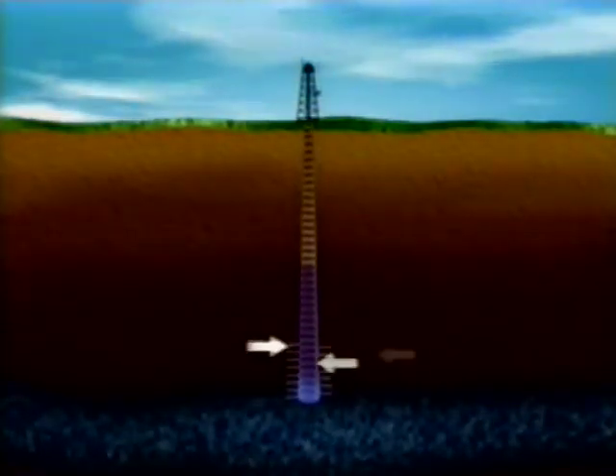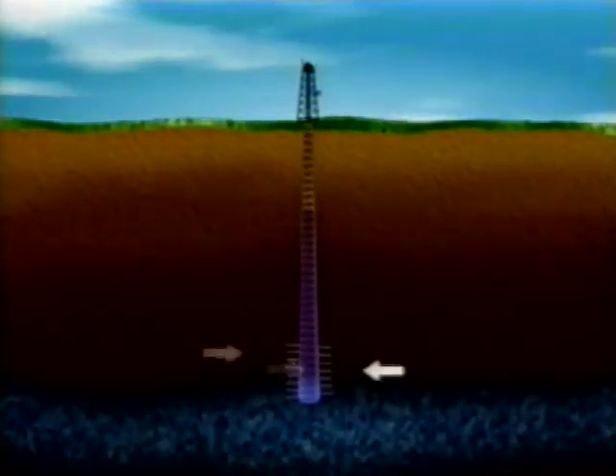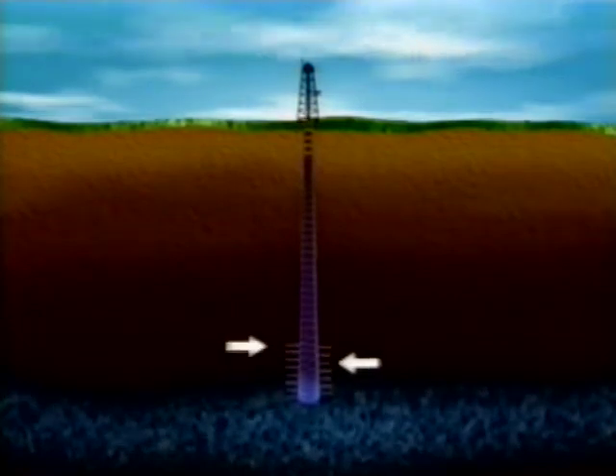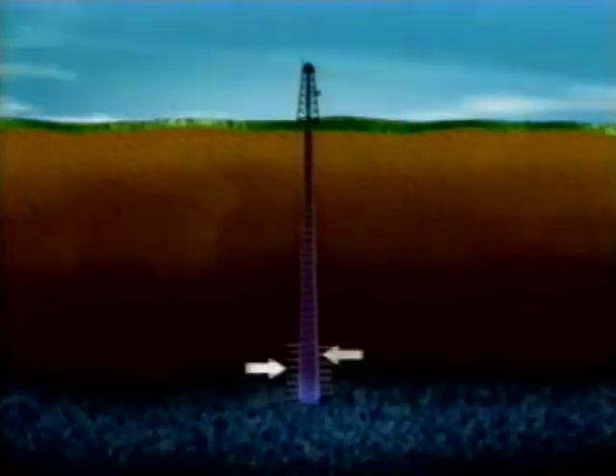A more severe situation arises in the case of the breakthrough of injected seawater, which is often high in sulfate salts, and its mixing with formation water containing a high percentage of other salts can result in barium or strontium sulfates being deposited. These scales are very hard to dissolve.